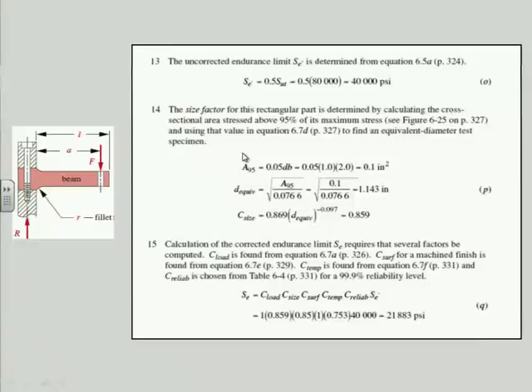So C load is equation 6.7A, and that, you may recall, has only two values. It says for bending, use 1, and for axial, use 0.7, I think it is. And this is bending, so it's 1. And then the C size factor, as we just discussed, comes out of this. There's the equation that I get to approximate at 0.859. C surface, machined finish, equation 6.7E tells me that 0.85 is a good estimate for that. C temp, this thing is at room temperature. Reliability, 0.753. Did I say what percent that is? Yeah, 99.9%.